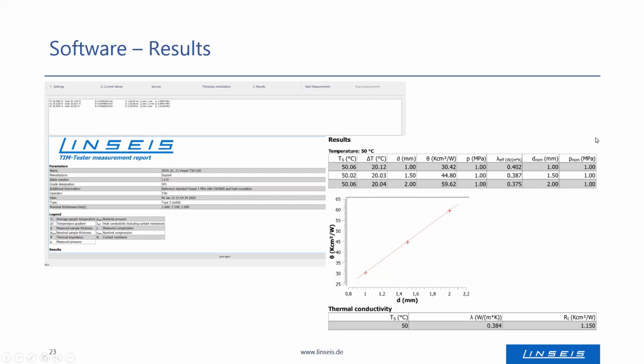In the report, one can also see the set values of the thickness and the pressure, where one can check if everything worked correctly. In this case, it was very good, since the given thickness corresponds exactly to the measured thickness, as well as the contact pressure.